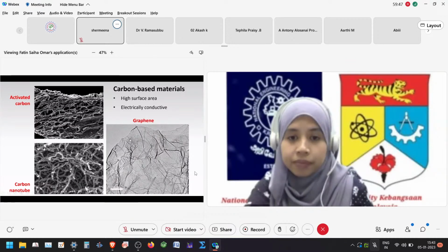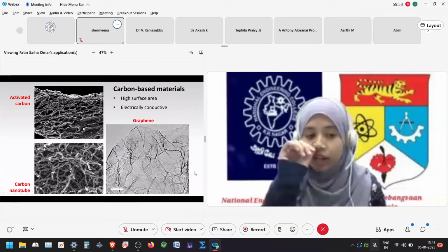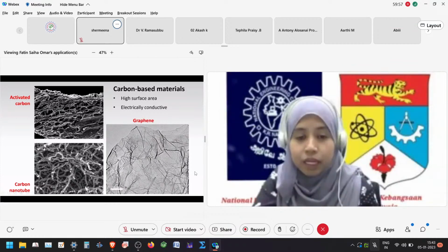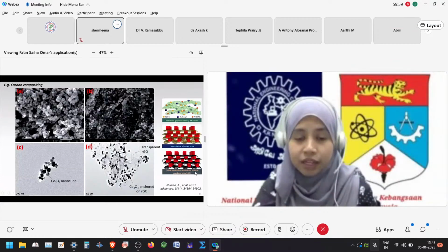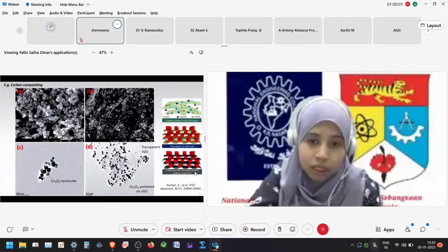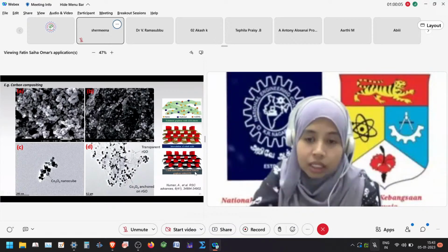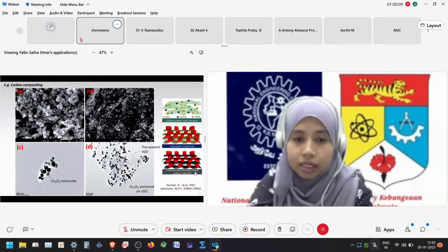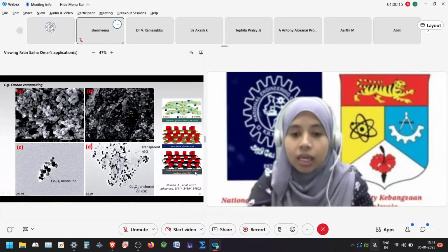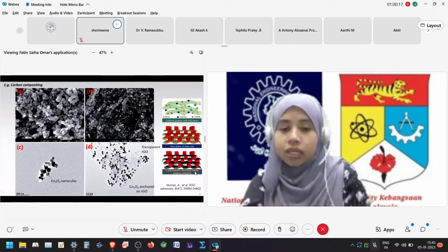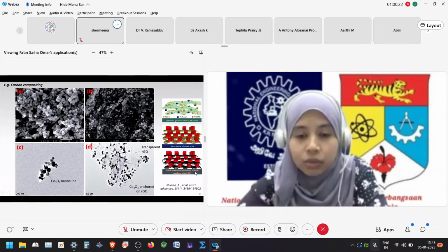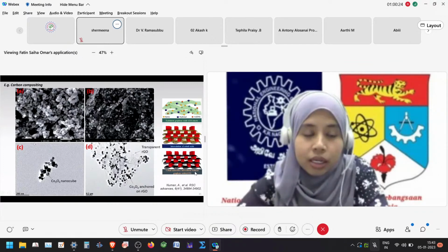This is graphene. Cobalt oxide nanocube by compositing the nanocube with graphene. So this translucent shade is the transparent rGO, and the dots are the cobalt oxide. So this image shows that the cobalt oxide is anchored on the sheet of rGO. So after we composite the cobalt oxide with rGO, we notice that there is enhancement in the electrochemical performance. So this is the reference.